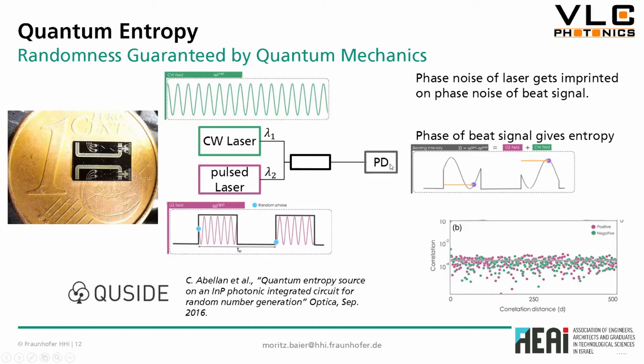that is visible on the photodetector. And now, because the optical phase at which a laser starts oscillating is completely random, and this randomness really goes down to quantum mechanics, you have a random signal that you can measure, namely the phase of a pulse on a photodetector, which really is random on a quantum level. Which is shown by this correlation function here. So you have a correlation below 1 in 1,000, no matter what pulse you correlate with another pulse. And so this can be used for QKD schemes where you need quantum random number generation.